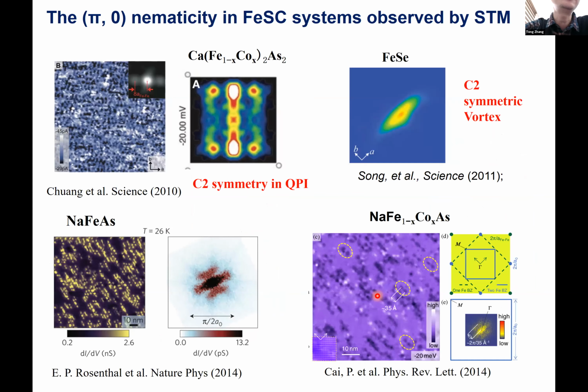So previously, people also used STM to measure the nematicity in the iron-based superconducting system. So for example, in calcium 122, the parent compound, they also see an anisotropic QPI, and in iron selenide, they observe such an elongated vortex core. These features are all considered to be evidence of the nematicity, but they are all along the pi zero direction. But our observation is that they are along the pi pi direction. So it's like a new kind of nematicity.